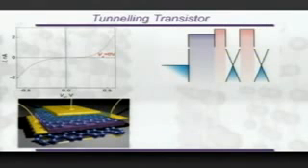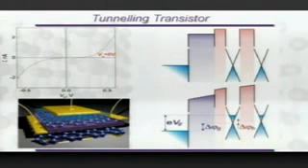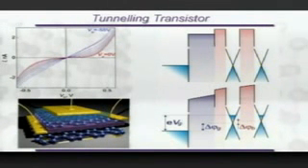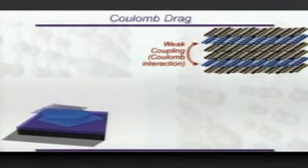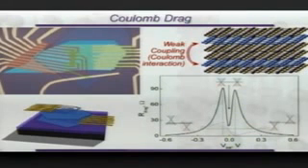We also made a transistor out of it. You put graphene, molybdenum sulfide, boron nitride, molybdenum sulfide, graphene, and then you can gate it, and you can tune the current through this stack, and it acts as a transistor which actually works, and it can be used in integrated circuits. And because it is vertical, we don't have a problem with sizes. We can make it as small as we want. And then the type of physics which we find in those materials is extremely exciting, because we can really make very complicated structures now. And that's exactly where we and many other labs are going now.